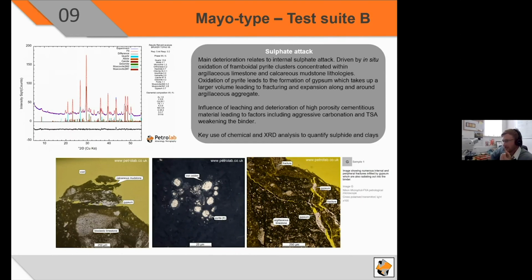In this case, XRD analysis is used to confirm the presence of sulfide minerals and clays that define the argillaceous limestone and calcareous mudstone lithologies. While the chemical data is specifically the total sulfur, the acid soluble sulfur, and the water soluble sulfur, are used as a way to quantify the amount of sulfide and sulfate present within the aggregate, which is acting as a deleterious mechanism in this case.